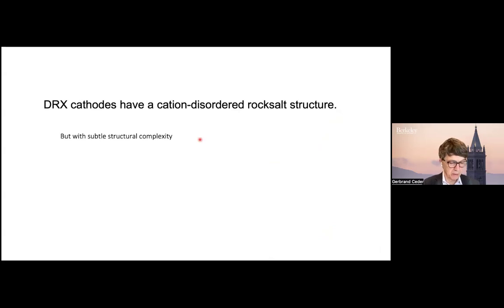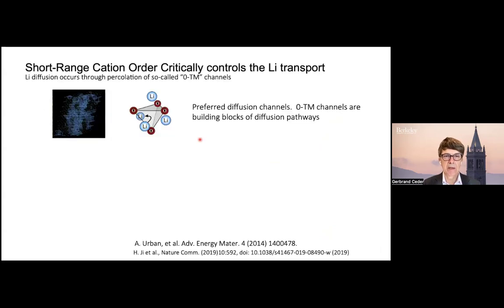I want to come back a little more to the structure because that becomes important. If you look at these materials in X-ray diffraction, they look very simple. They're truly a rock salt, so fully cation disordered. But what we have learned over the years is that there is subtle structural complexity that you cannot see in XRD, but that you have to control by compositional issues or by processing. Most of them relate to what's called cation short-range order.